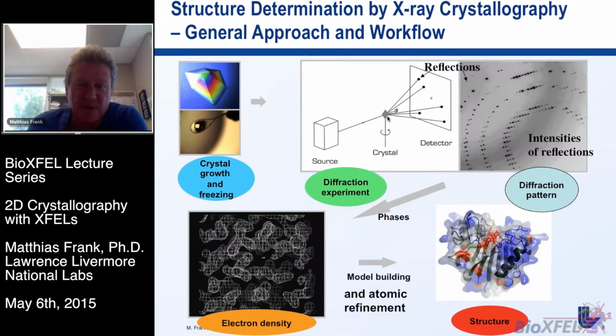And then, as X-rays impinge on the crystal, different planes in that crystal lattice cause X-ray reflections or Bragg peaks that you can measure with a detector. In a typical measurement, you slowly rotate the crystal. You get Bragg peaks from different orientations. And on the upper right is a diffraction image shown from a crystal. And those Bragg spots contain the information on the structure.